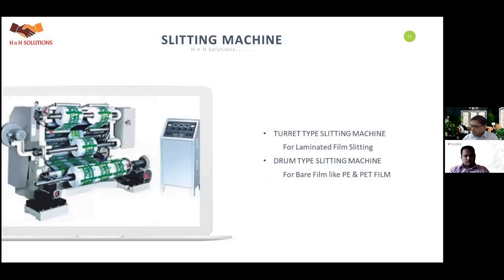Slitting machine. After lamination, we have to keep the laminated roll as it is at ambient temperature for a minimum of 72 hours for better curing. Then and only then can we start slitting. Majorly two types of slitting machines are available. Turret type slitting machine for laminated film, and the second one is a drum type slitting machine for bare film like polyethylene, PET film, BOPP, CPP, and paper.